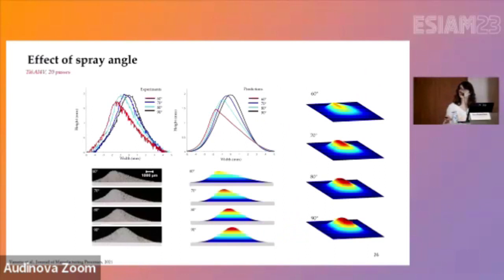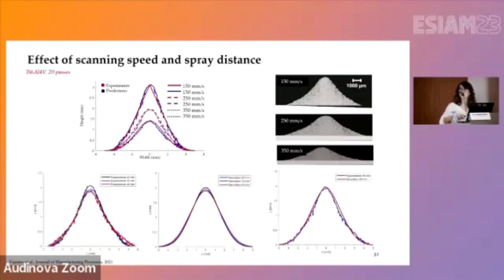Here you see the prediction of the model for the effect of spray angle, as we are changing the angle of the nozzle with respect to the substrate. And here are the results from the experimental data that has been digitized in 2D and 3D. Very good match also in terms of spray angle.